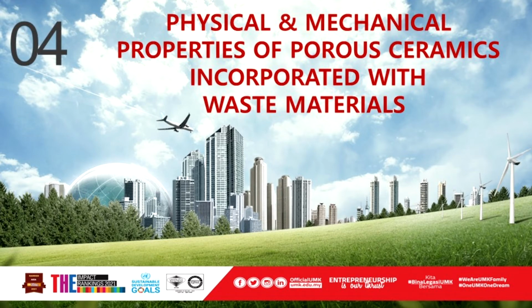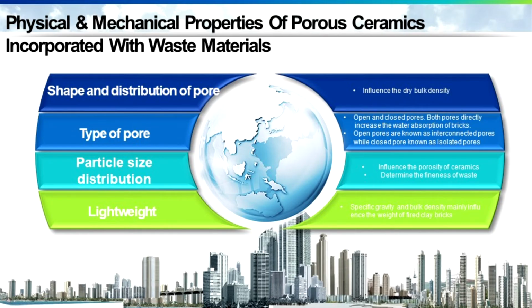Ladies and gentlemen, several studies have investigated the physical and mechanical properties of the waste containing porous ceramic. The physical and mechanical properties of the porous ceramic are controlled by the amount and shapes of the PFA added, pore types and particle size distributions of the PFA. For instance, micrographs of porous ceramic with irregular, spheroidal and longitudinal shapes can be obtained due to the additions of graphite waste, yeast and rice husk ash.